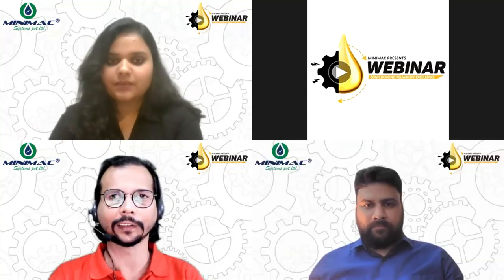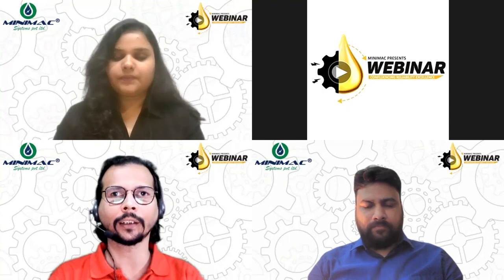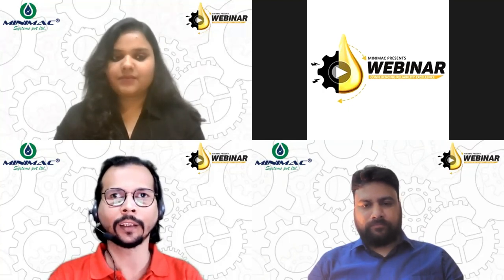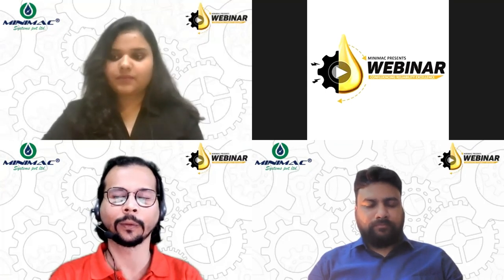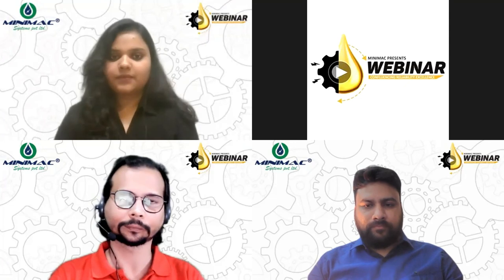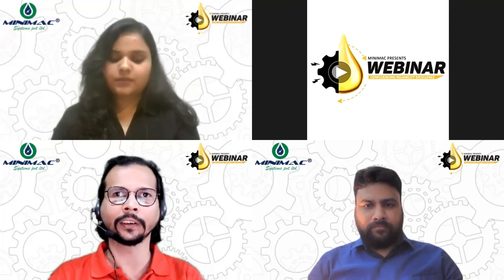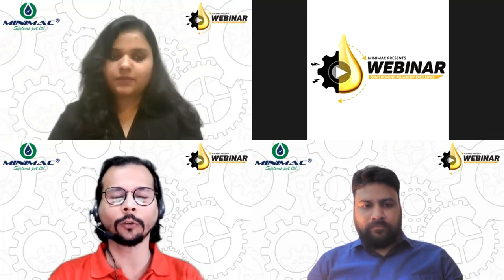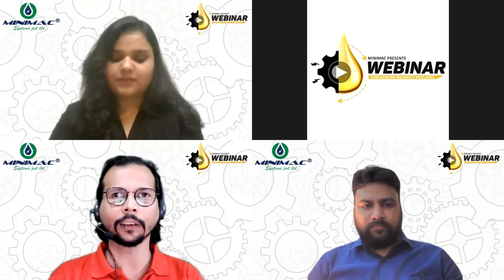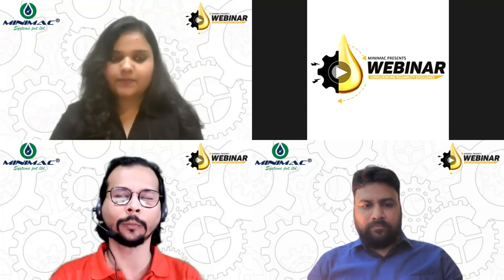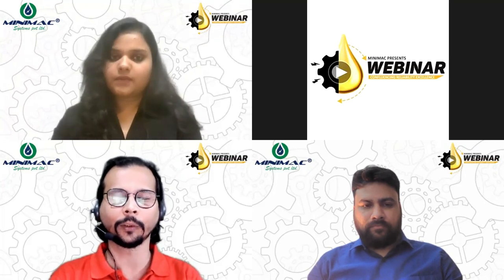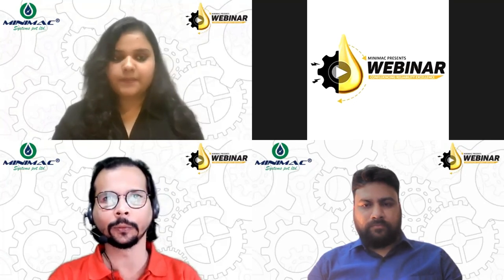When we say about the maximum allowed temperature, first point will be what temperature is defined by the oil manufacturer. That will be around 110 degrees Celsius. Then what temperature is recommended by the turbine manufacturer or turbine bearing manufacturer? That is around 105 degrees Celsius in the case of Babbitt coated journal bearing. So in general practice of steam turbine and gas turbine, we don't go beyond 105 degrees Celsius. And in case of hydro turbine, limits are different. We don't go beyond 85 degrees Celsius. But if you are talking about any specific turbine of any particular application, we need details to define the limits.